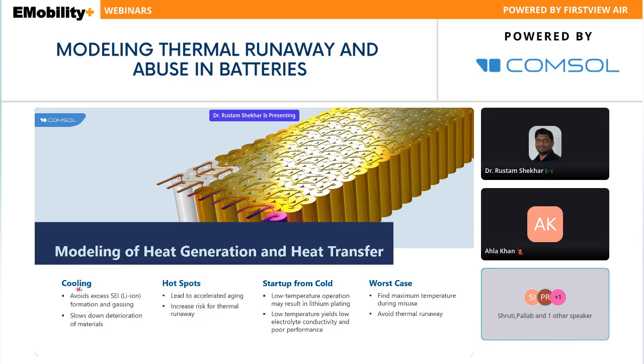So either it is cooling of the battery or identifying the hotspots, in both cases we want to cool down the batteries by adding heat transfer to it, and the combination of battery modeling and heat transfer will give you the complete picture of this cooling and hotspot formation. In some cases, when you are operating at low temperature or in a cold environment, it may lead to lithium plating, and low temperature also leads to less electrolyte conductivity. That means performance also will be very poor.